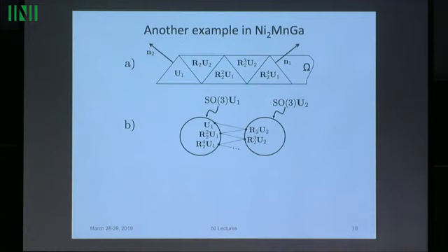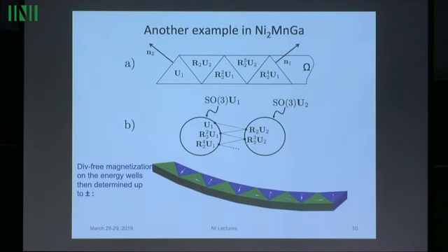And this is quite generic. You can do this in many cases. And then, so what does that mean? That means we've satisfied the compatibility conditions, the rank 1 jump conditions across these variants. And now I can add the magnetizations, consistent with the energy wells. And so once again, there's no divergence, no poles on any of these walls. And actually the deformed shape looks like this.